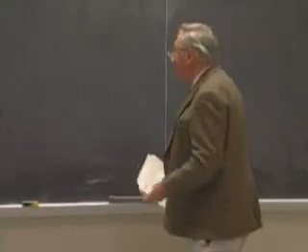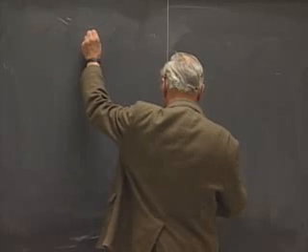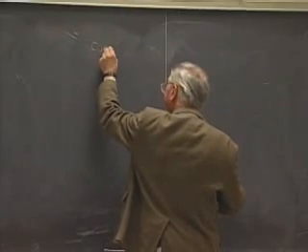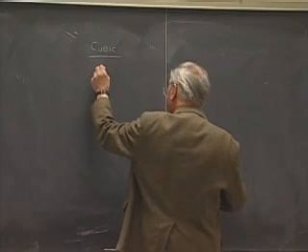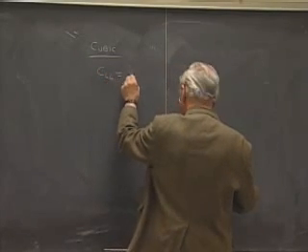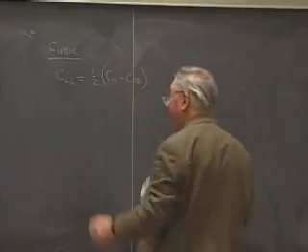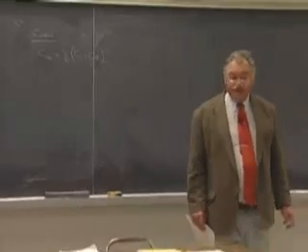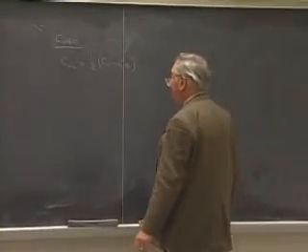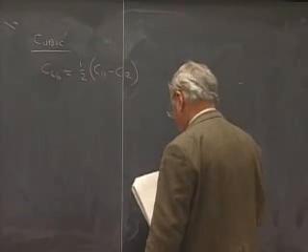Here's something curious. When we looked at symmetry constraints on single crystals, we found that for a cubic crystal, C66 had to be equal to 1/2 of C11 minus C12 if the stiffnesses were to be independent for all symmetry transformations.